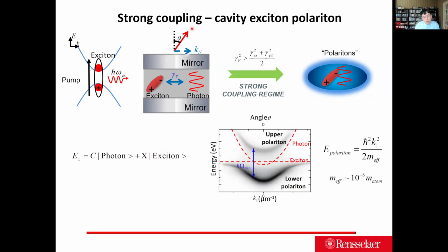So think about it. If we have a semiconductor and we try to measure the semiconductor's emission at different angles, essentially with different projections in the horizontal in K space, and we plot the K and E diagram, essentially the momentum versus energy diagram, we are going to observe the exciton become a flat line. That means no matter what angle you measure the semiconductor's exciton emission, it essentially shows the same peak. If we remove the semiconductor and just put a dielectric there, we are going to measure a photonic band with a dispersion.